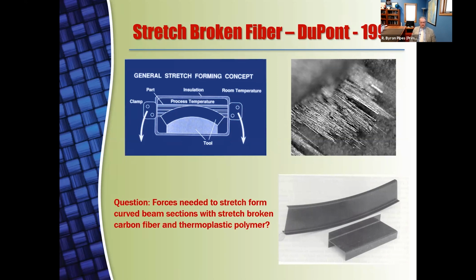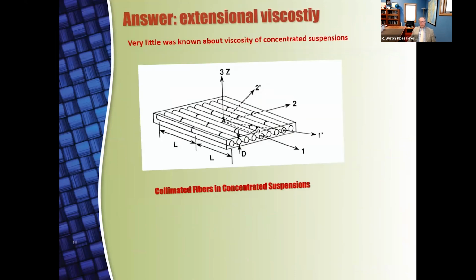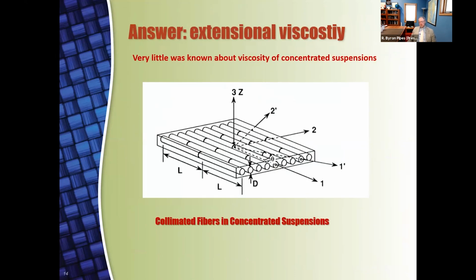Well, obviously it would be a viscosity. And so I began to look at that problem by formulating it very much as we had formulated the unidirectional continuous fiber system. But here we had to think seriously about concentrated suspensions. We had fiber volume fractions that were 60%. Typically, dilute concentrations were down in the range of 5% or lower. And indeed, no one had worked at the level of 60% volume fraction in these suspensions before. So it presented an interesting idea, but a nice challenge. And of course, a typical engineer with a challenge simply looks at the kinetics or the kinematics or some mechanistic idea from which you can derive the response.